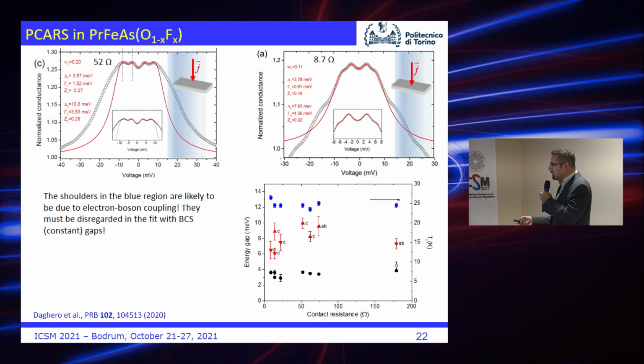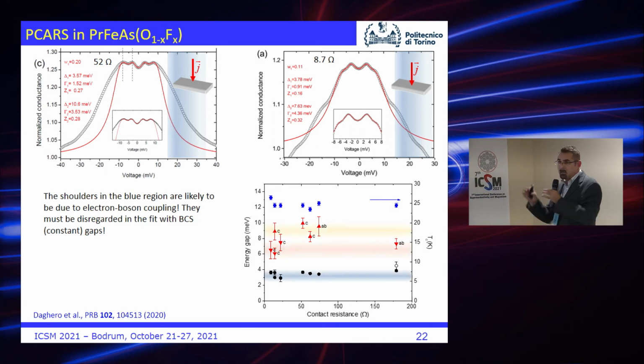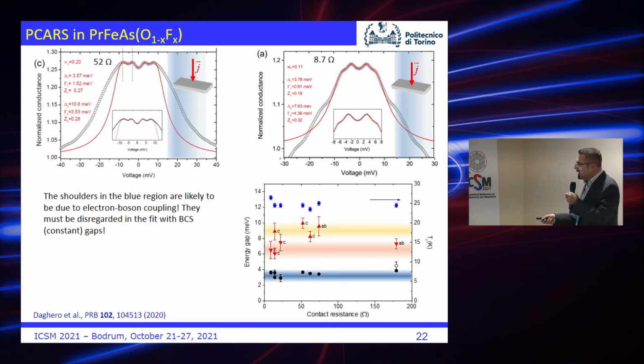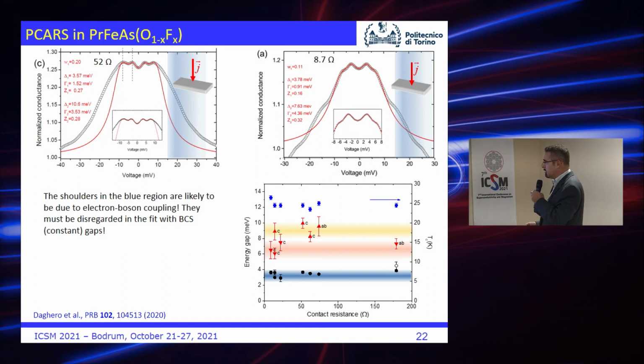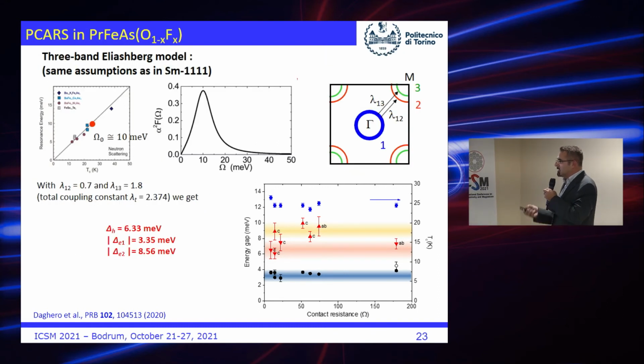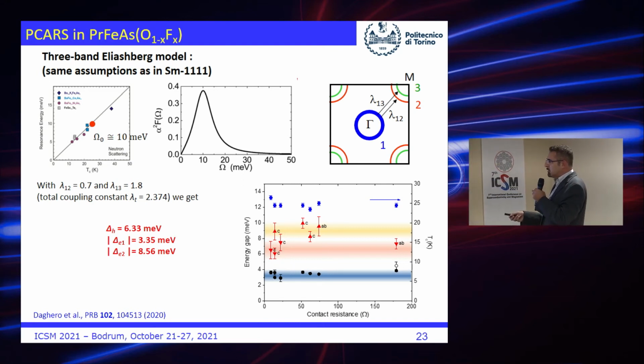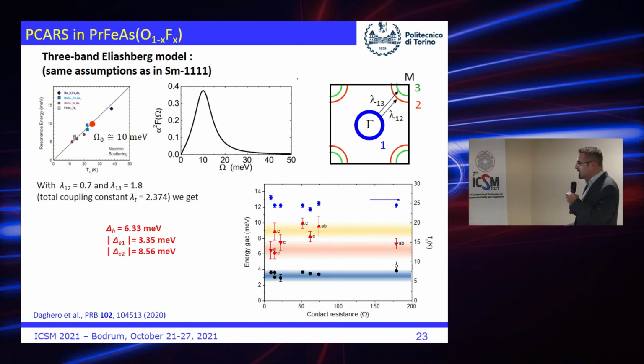And in principle, looking carefully, it seems that there might be 2 different, let's say, areas where the gaps are concentrated. Now let us see what Eliashberg equations tell us. Again, the same machinery. I do not repeat anything. So now we choose the boson frequencies to be in agreement with this. That means 10 millielectron volt. We use the same shape, the same structure of the Fermi surface, and we get these 3 gaps.